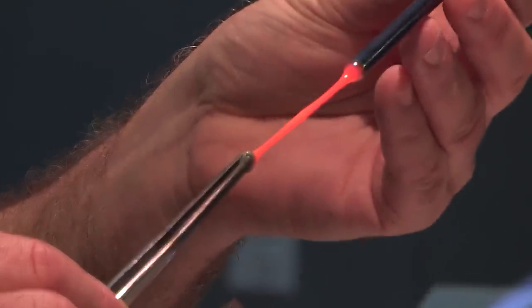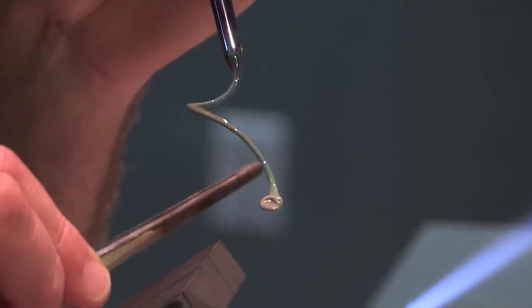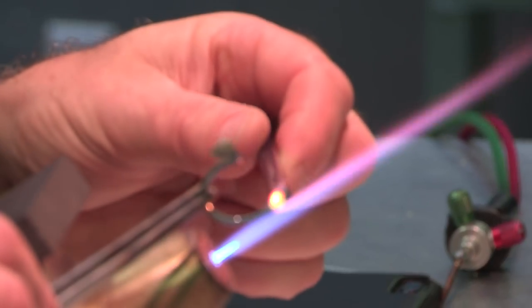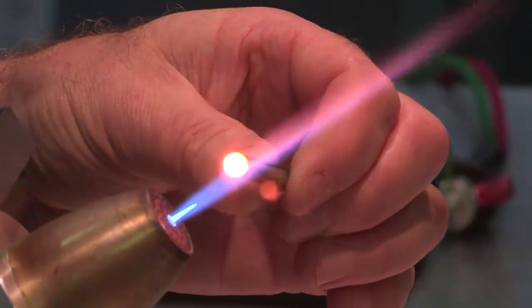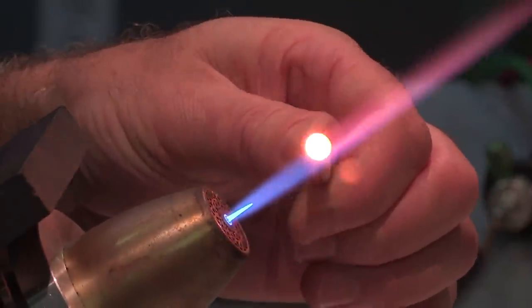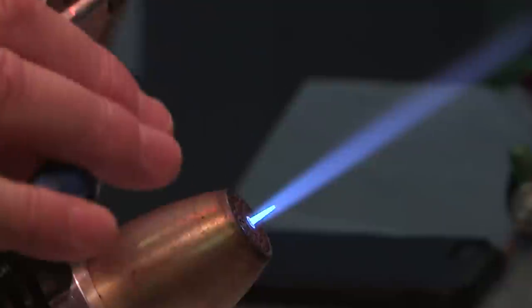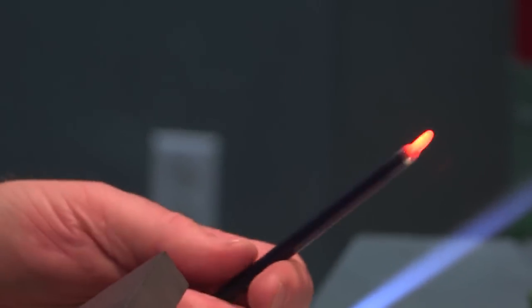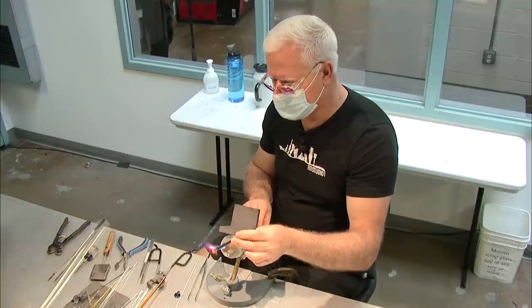And I'm just going to grab onto it and do a little pull. And what we should be getting is a series of sage greens and some blues. Right? So lovely pastel green here, some striking of blue. Right? Fine. To get it to move more towards the caramel spectrum, we're going to first put it in an oxidizing flame. And then we're going to reduce the oxygen. And this is why I say it's either one or the other. So let's flatten it a little. Still give it a little bit more heat. Great. Now we're going to cut that heat out. We don't have to wait with this one.